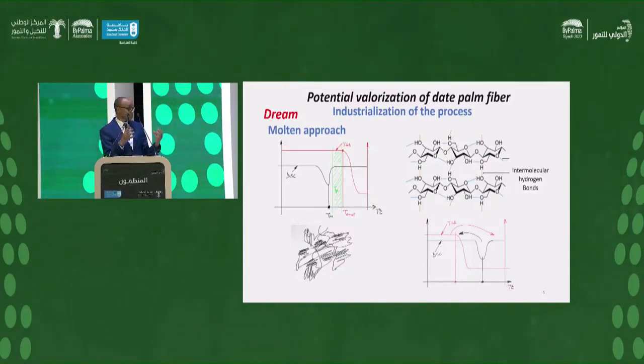We can improve the adhesion at the interface with different techniques, different functionalization, or the development of a new molecule to bridge between the matrix and the reinforcement, but we still have the degradation and the change of color of the material. And color is decisive in industry, because we must have color neutrality to add a master batch of color and produce the part in a specific color.